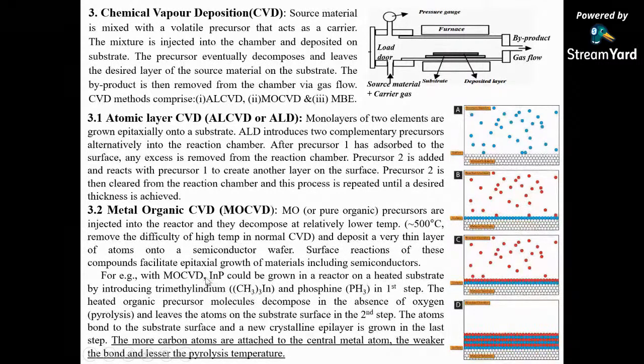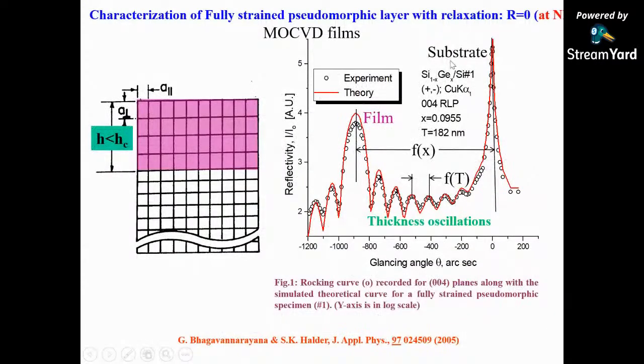And in this, suppose we want to make indium phosphide layers, we have to take trimethyl indium and phosphine. These will undergo reactions at the substrate, which is kept at something like 500 degrees centigrade. Then a reaction takes place, the residual gases will be evacuated, and a pure indium phosphide layer will be formed on this substrate. So we can characterize by high resolution XRD and epitaxy methods. And you see, below a particular critical thickness, if you make a thin film, it will be very well matched with the substrate. It will take the exact lattice constant of the substrate. So it will very well match this a parallel.